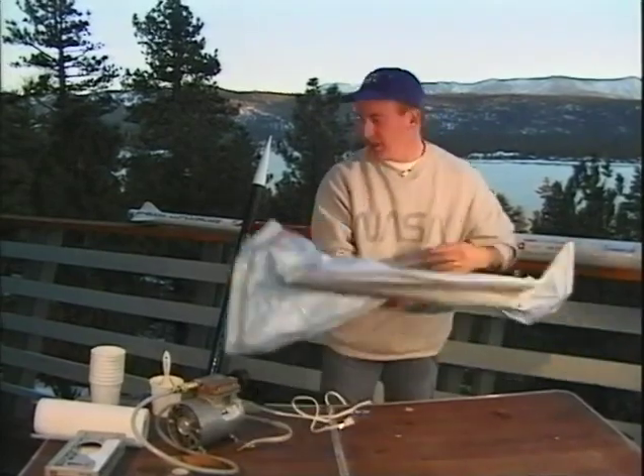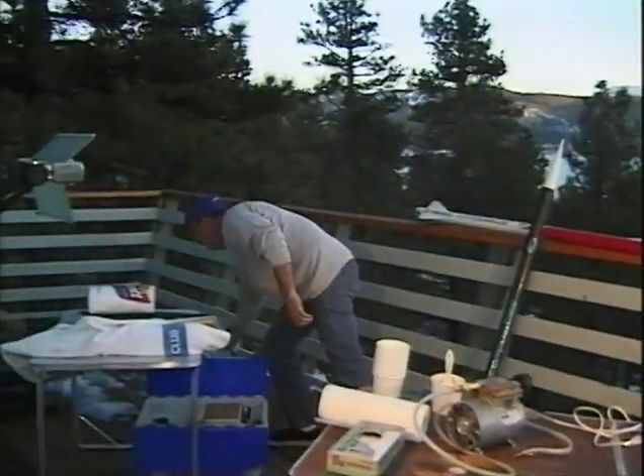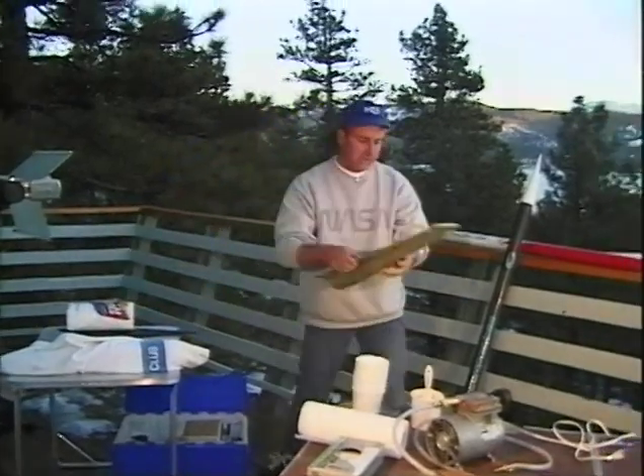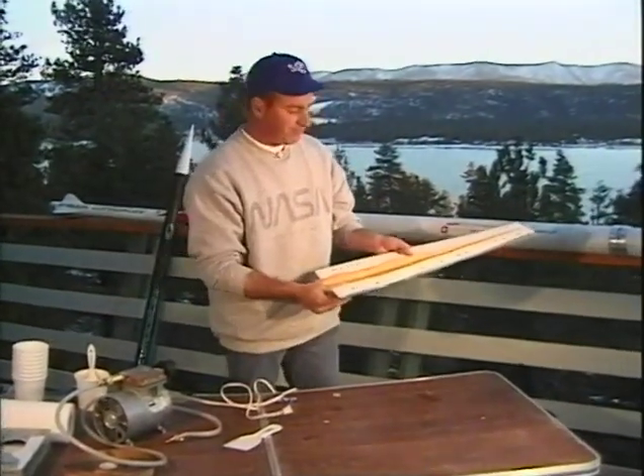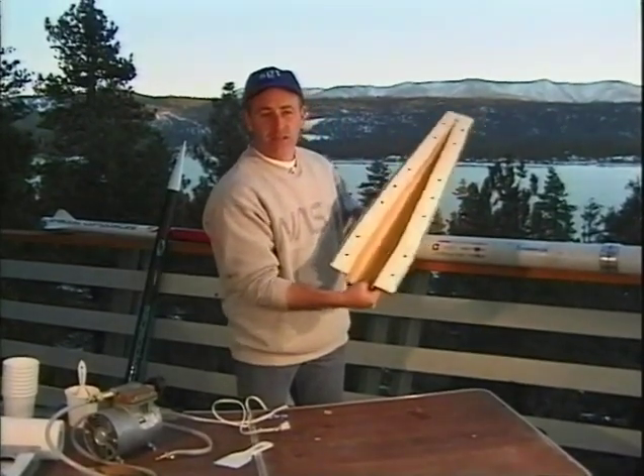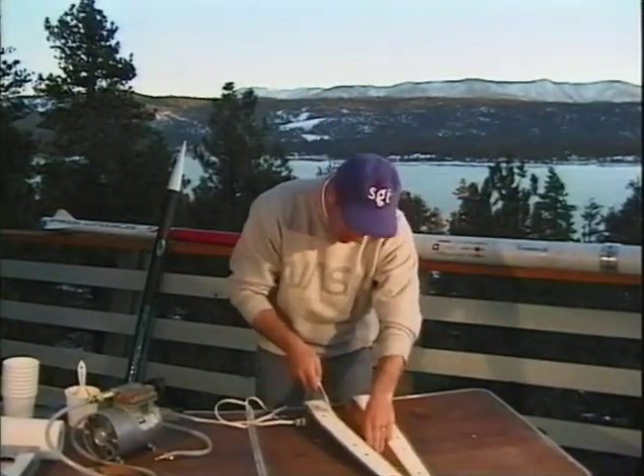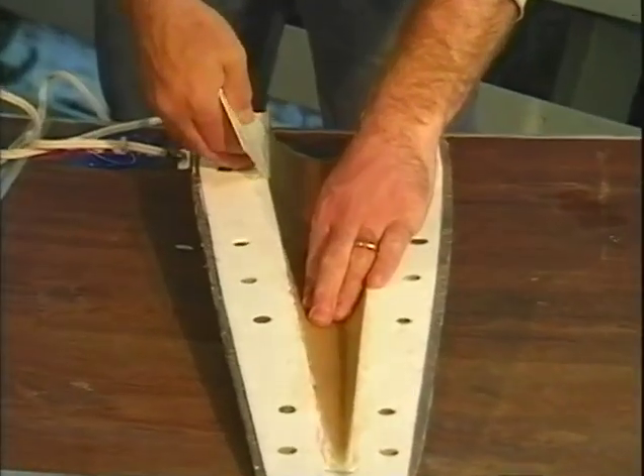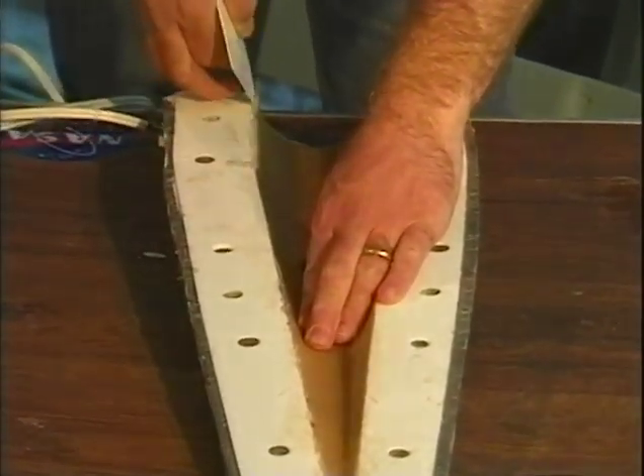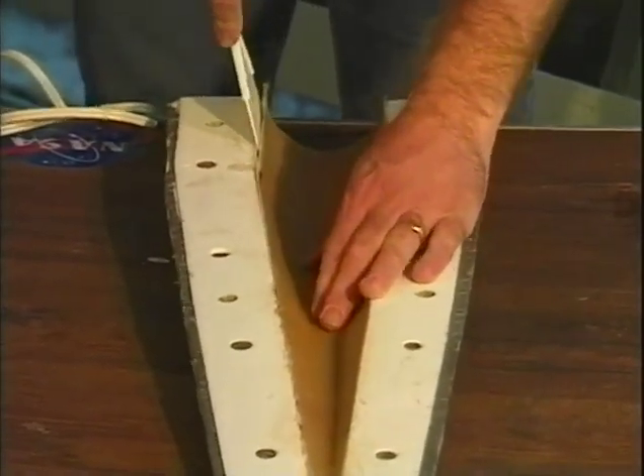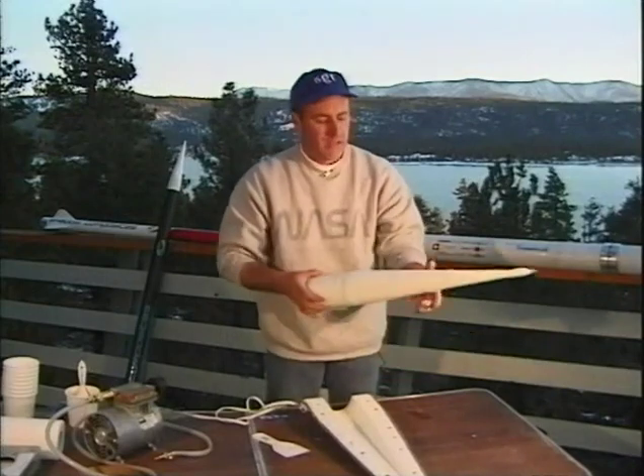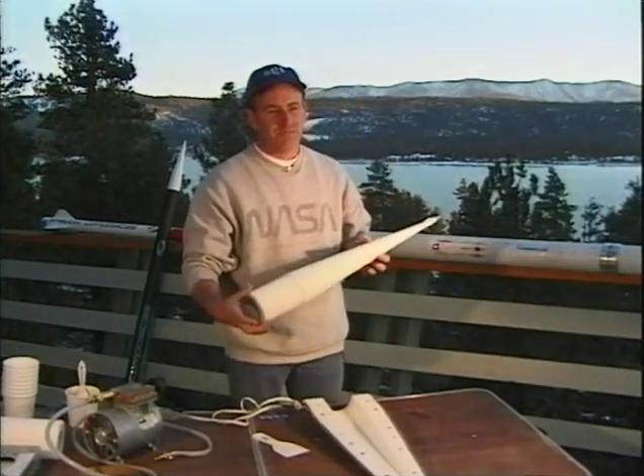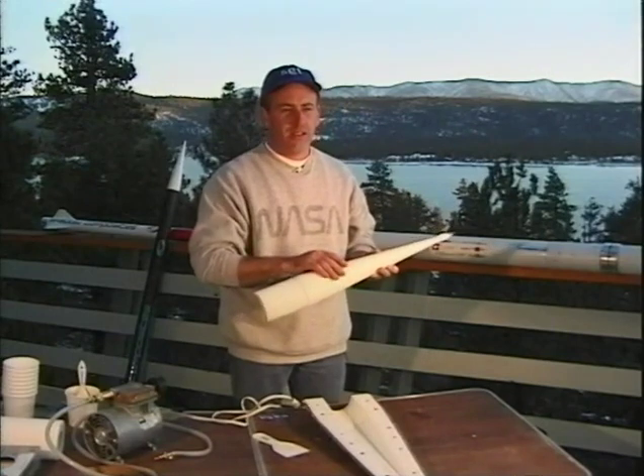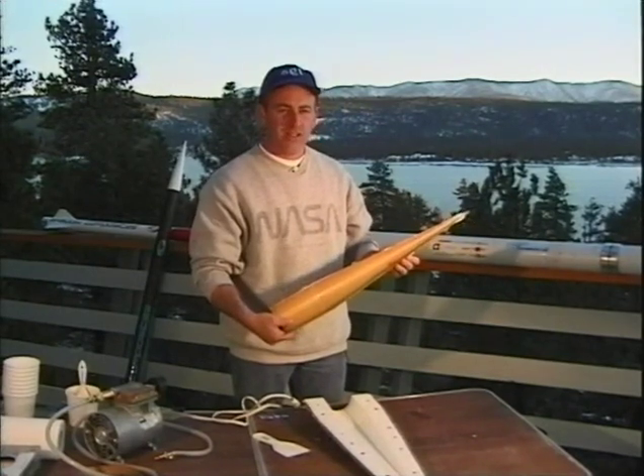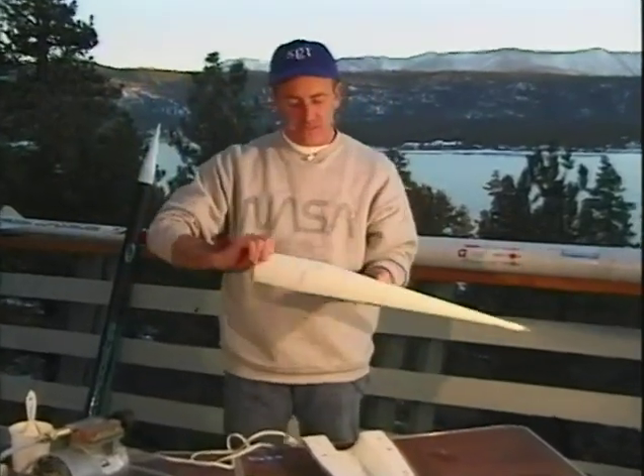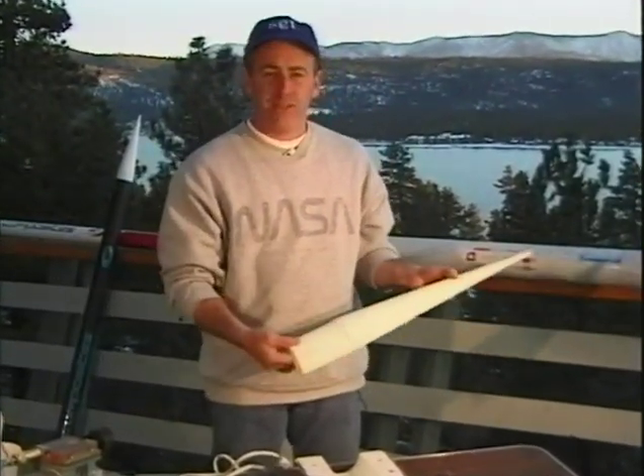So we'll take it off vacuum and I'll show you what we get. This is the other half of the same mold with the same Kevlar part. And we'll just go in and start to release it. And it should pop out any time. There we go. And this half of the nose cone is out of the mold. You see the white surface coat layer, and on the inside you see the Kevlar. Okay? That's a strong piece for half a nose cone.